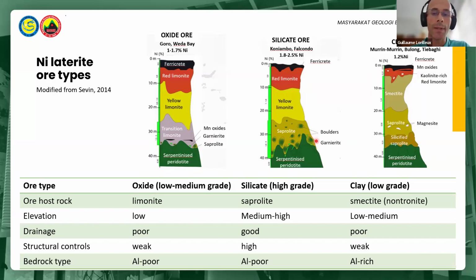The silicate ore is characterized by nickel-rich hydrous magnesium silicates in saprolite and generally presents high average grades varying between 1.8 to 2.5% nickel, again, depending on the cutoff grade. This ore type is generally associated with good drainage, medium to high elevation, and strong structural controls.